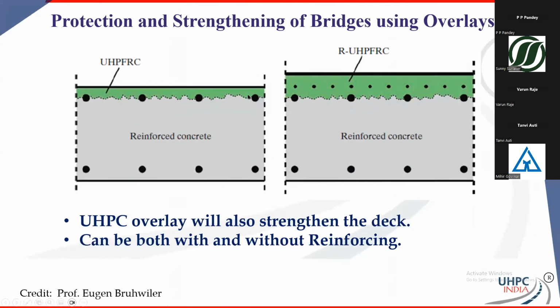Another way, over the bridge decks, UHPC is put as a small layer, about 30, 35 mm, maybe up to 40 mm, right? And it safeguards your concrete members below because it's highly impermeable. Number two, you don't need a wearing course. So lifelong, you can do without a wearing course because the abrasion resistance is also extremely high. If I didn't say about impact, the impact resistance, in fact, is also very, very high.